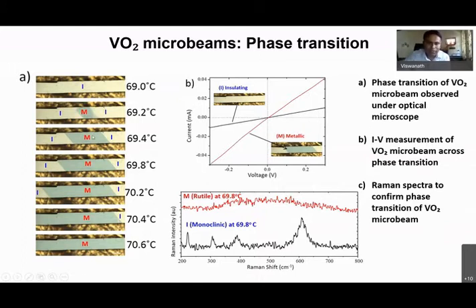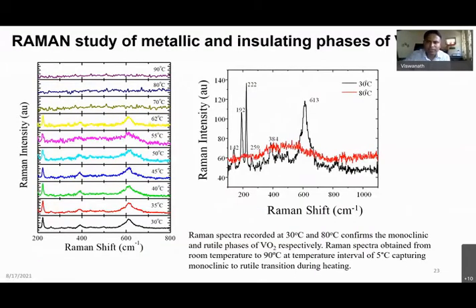We have actually confirmed that it is a metallic and insulating state by looking at the IV. IV measurement will tell us whether it is metallic or insulating. We also carefully looked at the Raman spectroscopy. In Raman spectroscopy, for the metallic state, due to the polarization absence and so on, you will see the peaks disappearing. Whatever the signature peaks of vanadium, oxygen, the vibrational modes, they will disappear when it goes to metallic. So we know by Raman spectroscopy and IV measurement that it is a metallic domain and an insulating domain. And the growth dynamics we also know. Again, I'll skip the Raman spectroscopy for the benefit of time.